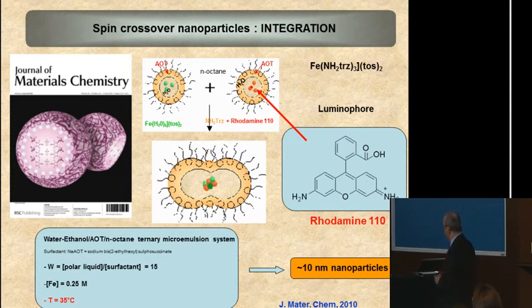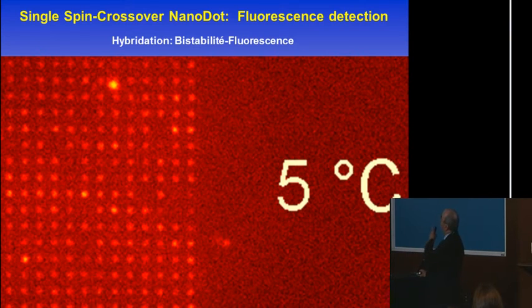What you can see now, when we combine the quantum dots with the rhodamine in the system, here you have the system in the low spin form. In the low spin form, as I told you, it absorbs the rhodamine light. Here in this situation, the light is absorbed. Now if I switch the system from low spin to the high spin, it is not absorbing. That means that we will see all the light of the rhodamine, as you can see here.